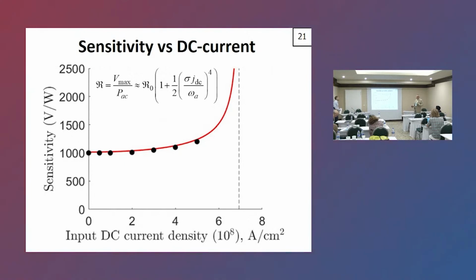Because if you reduce the volume, you will increase the influence of the noise. And signal to noise should be at least higher than 5. So you can't get, without cooling, a sensitivity higher than, say, several millivolts per microwatt.